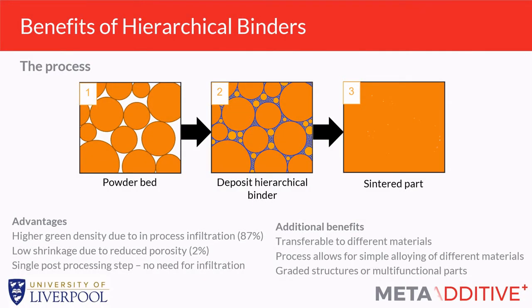So what we see is we go from this conventional 5-step to this new 3-step. So it's reducing the amount of manufacturing steps and reducing the complexity of the process. So we still have the same powder bed, but instead of infiltrating with a sacrificial polymer, we infiltrate and bind simultaneously with build material, this hierarchical binder. And that limits the shrinkage, but also lowers the sintering temperature and the length of time that we need to heat treat. So from our models that we've done to simulate this process, we've seen that for green part density, not final density, we can get infiltration of around 87% density.